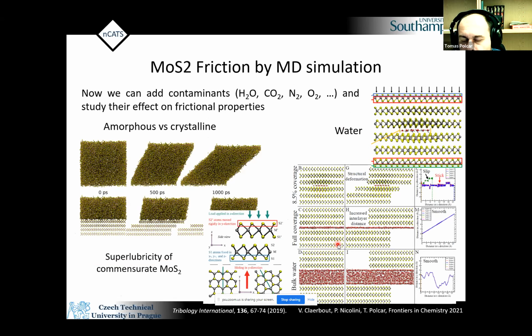So once we have that, of course, we can do more things. We can play with molybdenum disulfide. We can produce amorphous materials and slide them. We can produce crystalline materials and slide them. You can see the sliding of amorphous material. Then we have sliding of a combination, for example, of amorphous. We can measure friction there. The problem we have is that, of course, we are limited by a good force field, which is a huge issue for molecular dynamics in general, and especially for this problem in particular. And that's something which Ilia will discuss today. But even with a, let's say, non-perfect force field, we can get some interesting information about, for example,